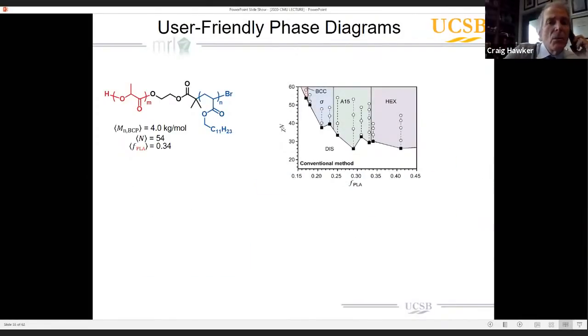So this is what Stephanie and Morgan were able to do using the conventional method, as I said, 15, 20 polymerizations and associated purification steps. And you can see that we get a reasonable idea of what the phase morphology is like. But remember, there's homopolymer contamination in this sample. The samples themselves, even though they're low dispersity, actually do have a fair amount of dispersity within the domain.